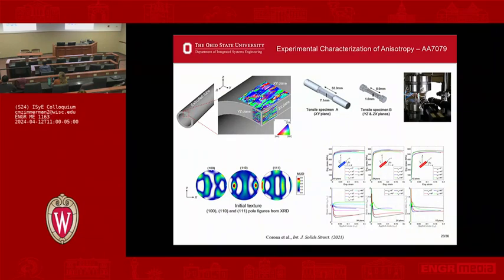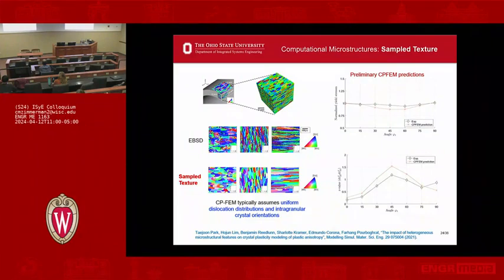What we did with our model, we actually took those measurements, went through that statistic, and created one that represents exactly the same material as that tube. We tested it. Here's the actual measurement. This is what we actually created from here. And it actually did a pretty good comparison. So again, this is important because it allows us to trust our model.